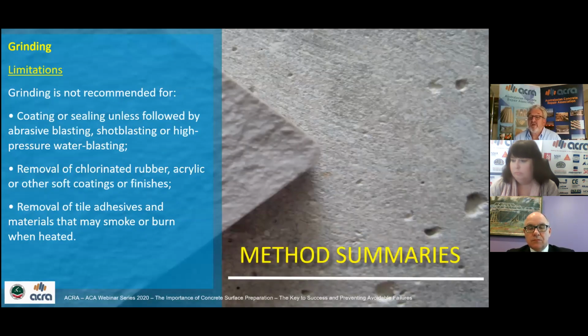Limitations: not recommended for preparation for coating or sealing, unless followed by shot blasting or high pressure water blasting. It's not suitable for removing thick coatings or acrylics and tile adhesives, and no good for trying to remove any material that may smoke or burn when heated.